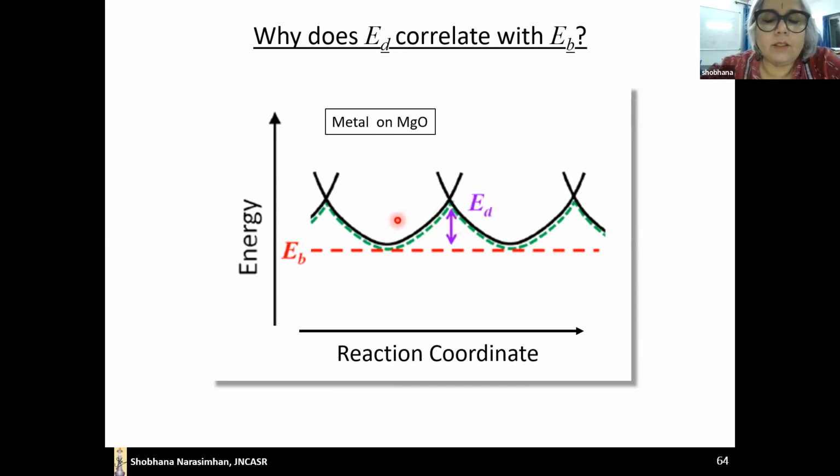So supposing we can think of the energy landscape of diffusion as a superposition of parabolas. Here I have drawn these parabolas, and this green thing is my energy landscape on which I'm diffusing. Then the depth of this minimum gives me the binding energy. And this height here, where the 2 parabolas cross, is the diffusion barrier.